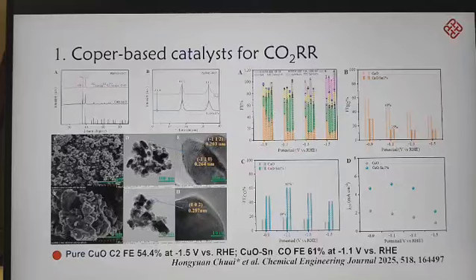From the electrocatalytic performance diagram, it can be seen that copper oxide primarily produces C2 products, such as ethylene and ethanol, achieving a total Faraday efficiency of 54% at minus 1.5 volts versus RHE. In contrast, tin-modified copper oxide mainly produces CO, with a CO Faraday efficiency reaching 61% at minus 1.1 volts versus RHE.